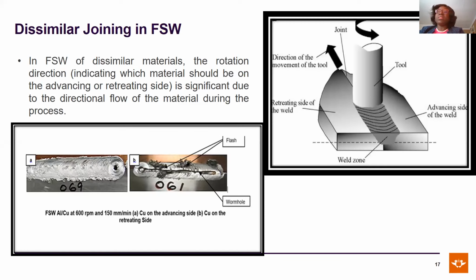So in dissimilar friction stir welding, dissimilar material joining, the rotation direction of the tool and where we place the materials is very, very significant due to the directional flow of the materials being joined during the process. So this is a basic fundamental research, which I have published. I've mentioned this in one or two papers, and other researchers have also published this as well. It is expected that other researchers coming along that need to join dissimilar materials do not need to go back to the basics of what we have done. This study is done and concluded that to enhance joint integrity, to have a good weld, the material with the higher melting point should be placed on the advancing side of the weld.